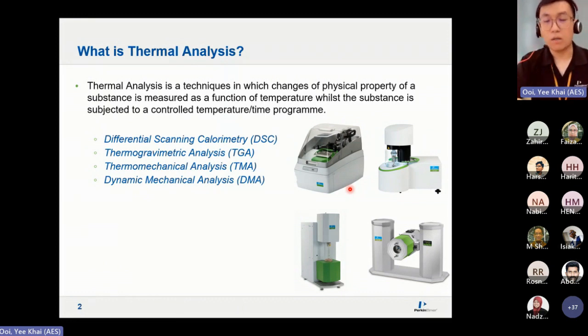So that is the job of STA, meaning at high temperature, because for DSC, usually we don't do sample decompositions. The maximum temperature that you can heat up to is not more than 800, which is more than enough already, because most of your organic materials or polymeric materials will start to degrade at 450 to 500 degrees C. Okay. Oh, going back to DMA 8000 just now.